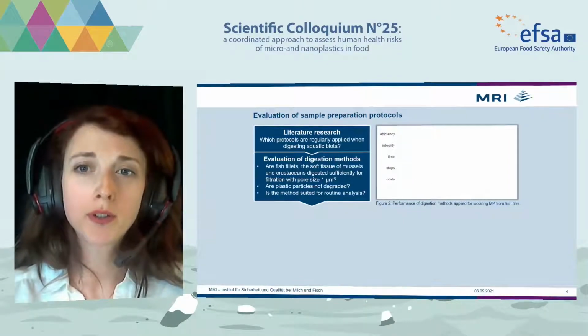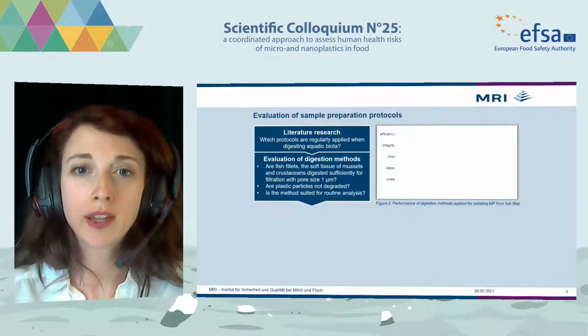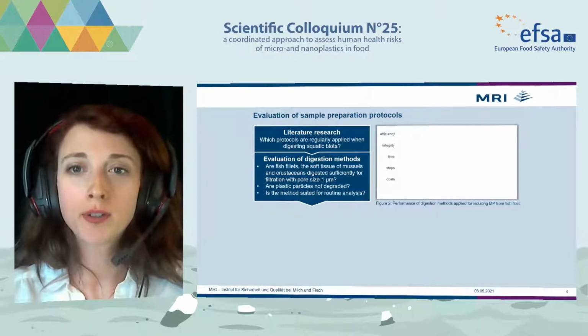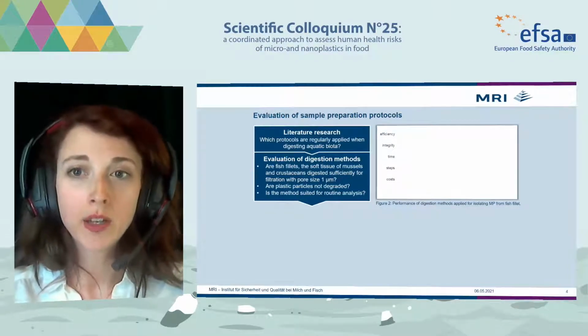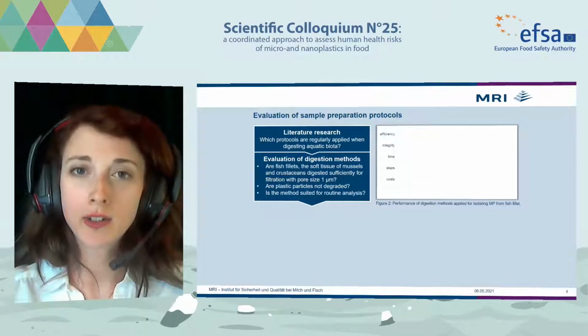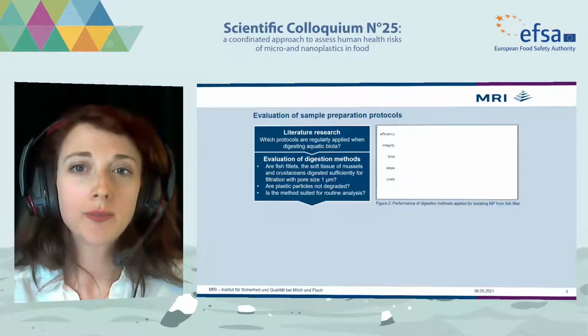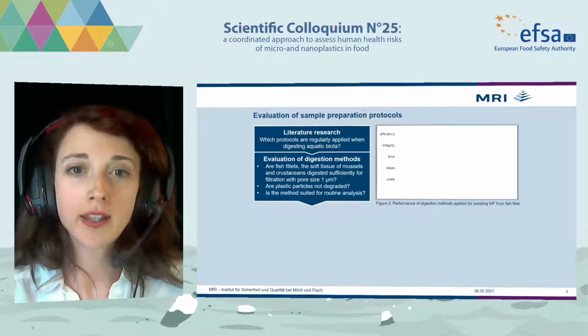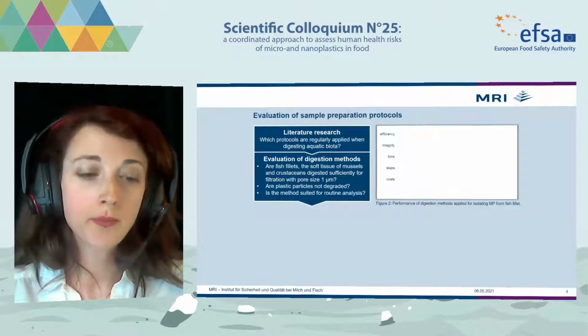Basically, the respective protocol should enable filtration of the complete sample with only one filter of the pore size of approximately 1 micrometer, so the protocol should have a high efficiency. However, degradation of plastic particles had to be avoided and the integrity of the polymers should be conserved.